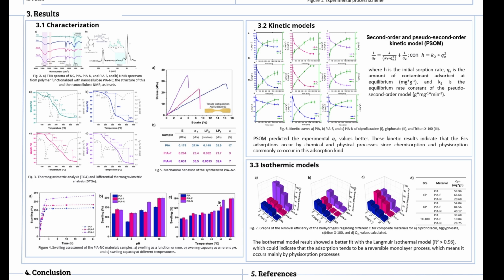Swelling is influenced by temperature and pH, with the highest swelling at 40 degrees Celsius and increased swelling in alkaline pH conditions. The nanocellulose presence and its fibrous structures in polyitaconic acid nanocellulose biohydrogels contribute to improving their swelling capacity.